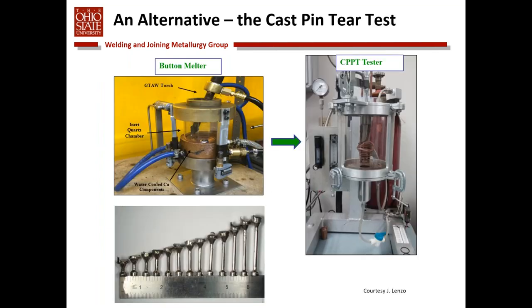So we've developed an alternative to the Varestraint test. We use, frankly, both the Varestraint test and something called the cast-pin-tear test. The cast-pin-tear test is shown here. It starts with melting a small button of material of desired composition. We put it in a test chamber. I'll show this in a little bit more detail in the next slide. But basically what we end up doing is casting a whole series of pins of different lengths of the material of composition of interest. These pins range in weight from about 12 grams up to about 20 grams. And so the amount of material required is fairly insignificant.